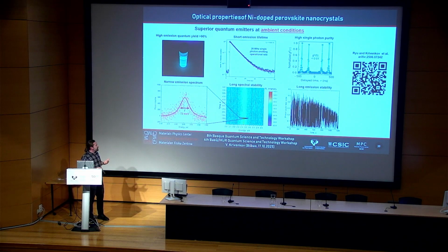To this moment, for our samples, we could achieve the spectral stability of our emission of a single particle at ambient conditions, room temperature, humidity, air, for more than 10 minutes for a single particle without any change of its spectrum. And in total emission lifetime, I would say these nanocrystals could be even longer than 20 minutes. To this moment, it is the highest stability level achieved at ambient conditions among all perovskite nanocrystals.